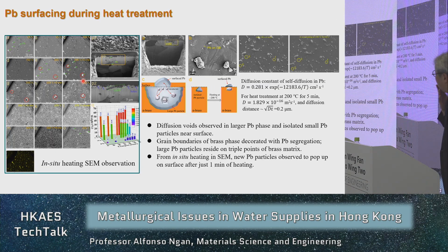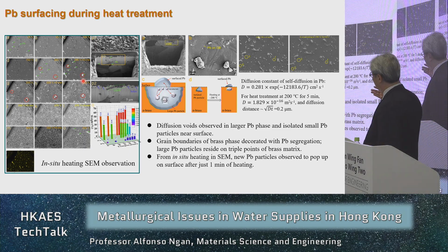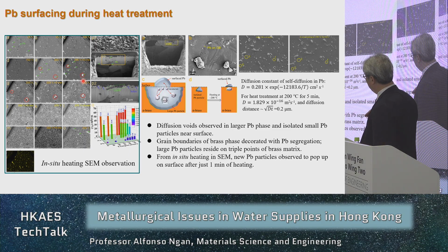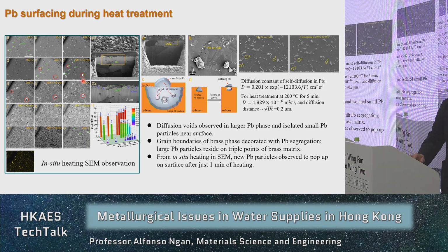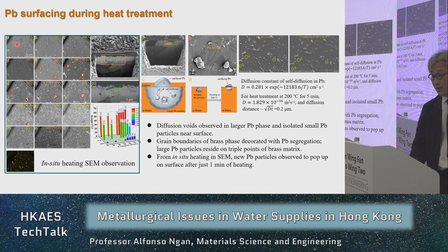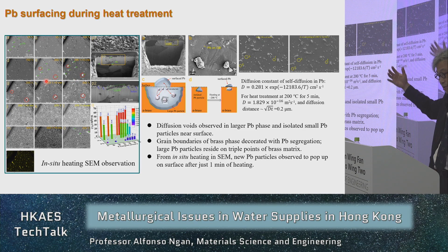This is another interesting experiment. We heat up the brass containing the lead inside an SEM. The white particles are the lead, and as you go from A, B, C onwards, the heating time or the heating temperature will go up. As you do more and more heating, there are more and more white particles coming out. So the lead is trying to diffuse to the surface.